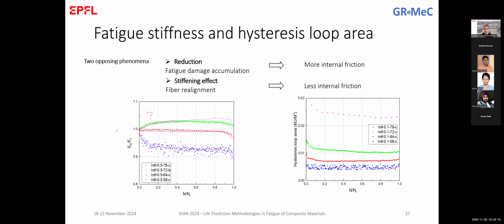When the fibers orient in a different direction and become aligned with the specimen loading, then the specimen is stiffer than before. And that's how we can explain this increase here.